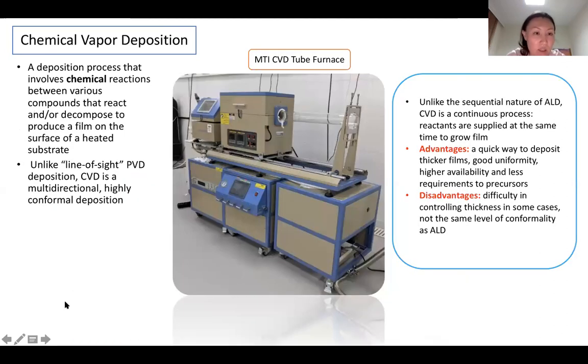Also, another chemical vapor tool is the CVD tube furnace. CVD is a multidirectional, highly conformal deposition. The advantages are quick deposition, good uniformity, high availability, and it's not as expensive as atomic layer deposition. The disadvantage is that the thickness cannot be so well controlled. So if you need very, very thin films, like several nanometers, this cannot be deposited with the CVD tube.